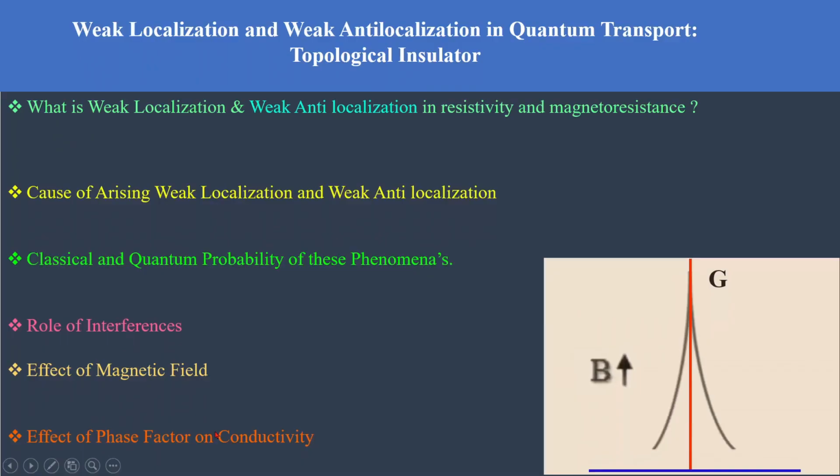which changes with the magnetic field, and may be by several other properties and disturbances. So this shows the conductance against the magnetic field. As the magnetic field is increasing, the weak antilocalization is suppressed, and at a certain value of the magnetic field, it is completely suppressed, and the conductance becomes flat up to a certain value of the magnetic field. Generally in very ideal systems, it appears in a very low domain of the magnetic field, which is generally minus 0.5 Tesla to plus 0.5 Tesla.